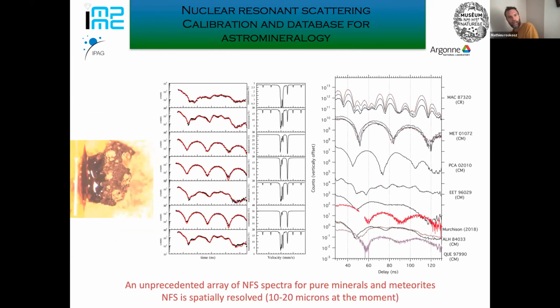We also played a little bit with natural meteorites, and you have examples here of big samples where we were able to map the iron mineralogy at the scale of a few tens of microns on billets. And so you can see easily the different kinds of spectra. Some of them are dominated by magnetite, some of them are dominated by anhydrous silicates such as olivine.